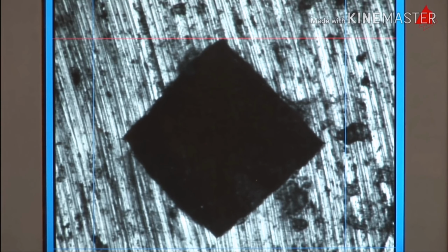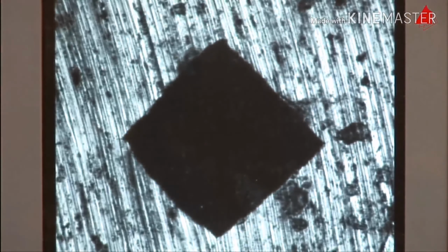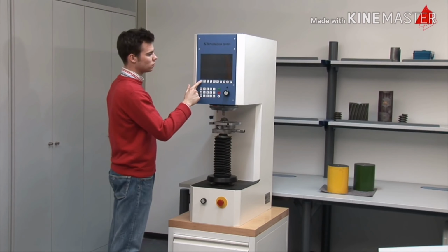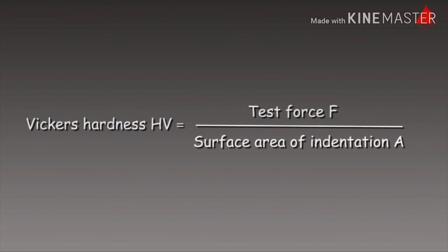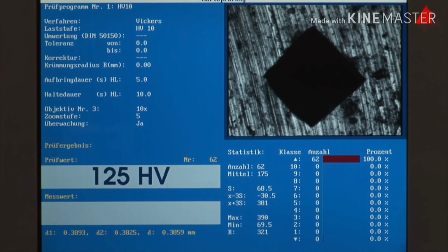With a control knob, the tester now places 4 measuring lines at the corners of the indentation. Doing that, he can easily measure the length of the 2 diagonals. Finally, he only has to push the input key. The Vickers hardness value will then be calculated automatically. It is equal to the test force F in the old unit kilopond divided by the area of the indentation A in square millimeters. The Vickers hardness of our compressor wheel is displayed on the bottom left-hand corner of the screen and amounts to 125.